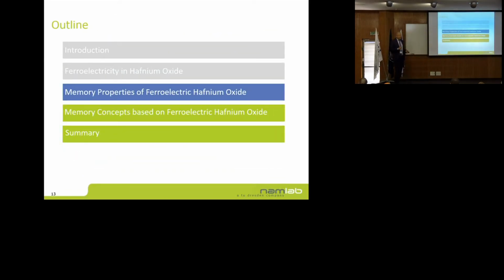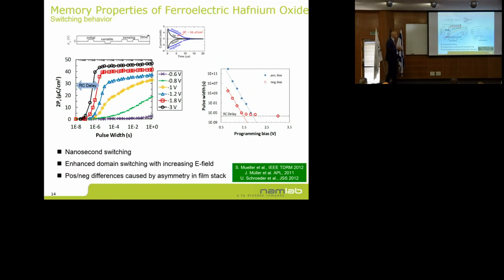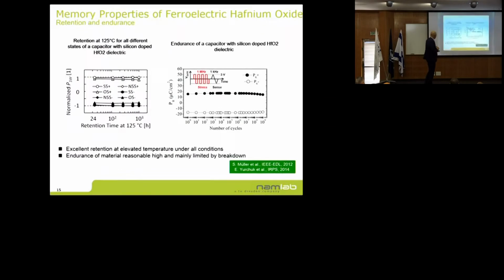But first of all, the first question is now answered. We can stabilize some sort of ferroelectricity in hafnium oxide. The second question is, is it useful for memories? So what we did, we looked at the switching characteristics, and you can clearly show you can make it faster with higher voltages. This is very consistent, and typically it can switch down to nanosecond speed, so that's pretty good, and we can really do reasonable programming of the device.